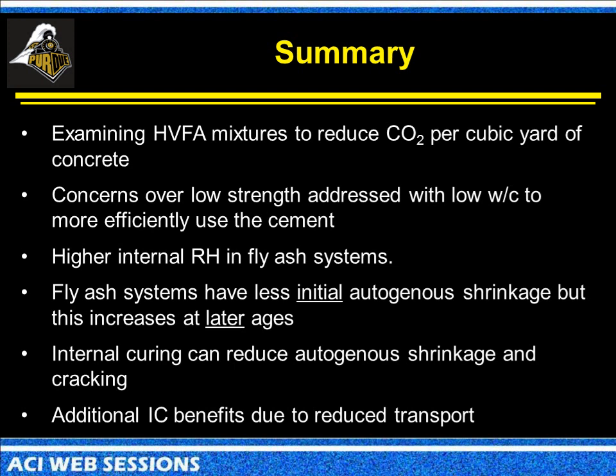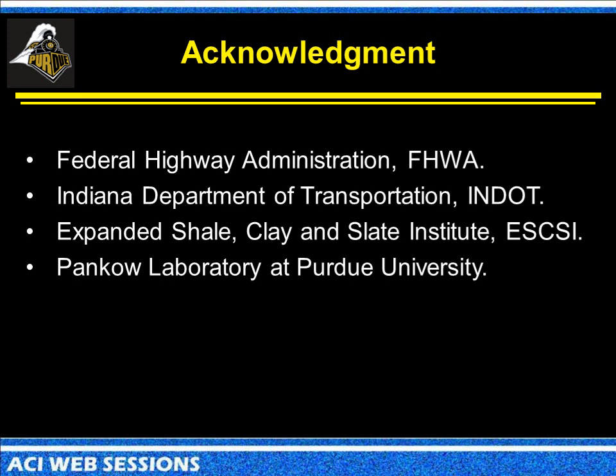We think that internal curing has the ability to reduce this autogenous shrinkage and cracking, and in addition to that, we're seeing benefits in terms of strength, but we think the real benefit is in reduced transport because we're allowing that additional hydration to take place in the system, which densifies the overall system. So with that, if there are questions.